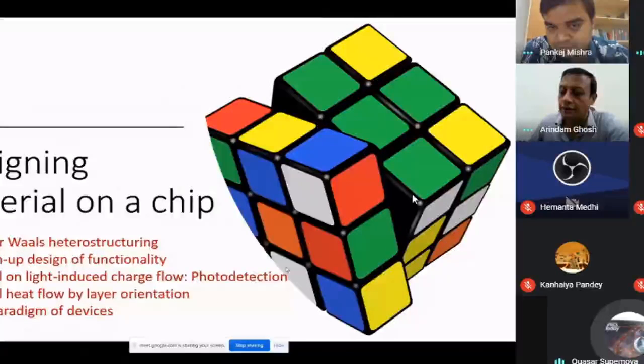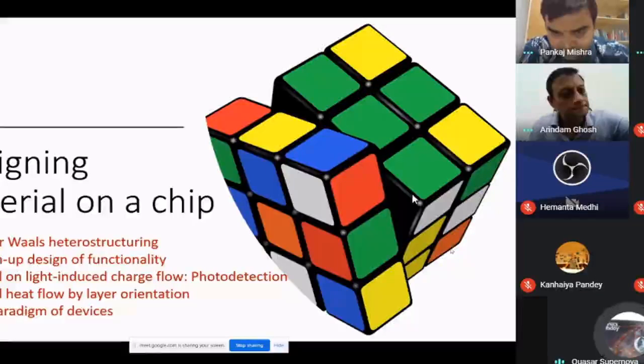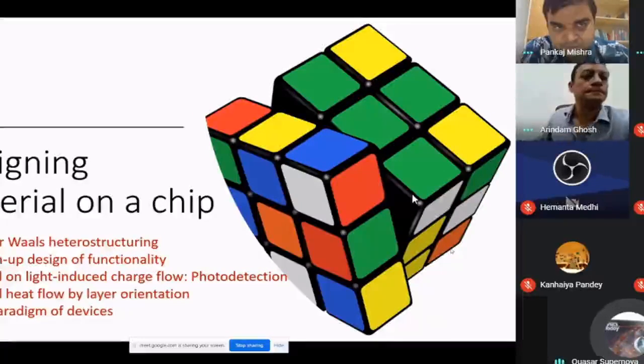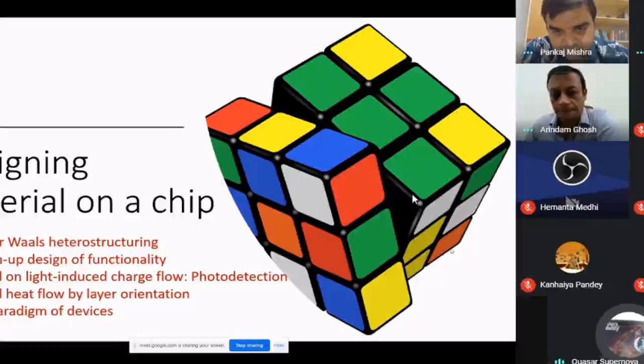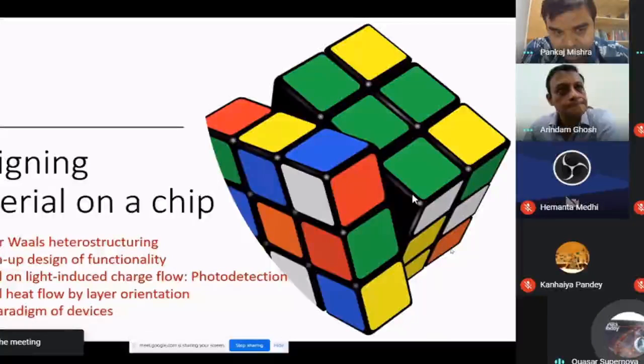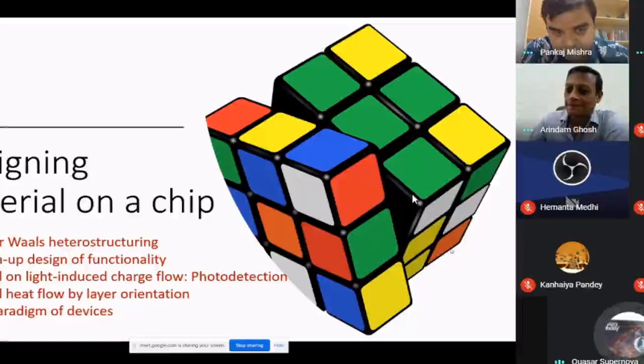Please. I have a question about some slide, but my question is rather silly, so please forgive me if it sounds very primitive. My question is the following: when you compare your experimental results with theoretical modeling, do those theories take into account the fact that screening is very poor in graphene, and an independent particle picture, I don't know to what extent people still rely on that. I'm not following the literature very closely. So to what extent do people still rely on this tight binding model without interactions in graphene? Because from my limited understanding, screening is very poor, and it may not be a wise way to do that.